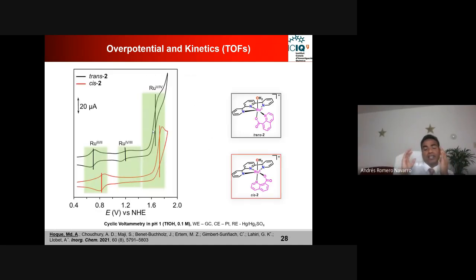So again, this is cyclic voltammetry. That is a very good analytical technique and assay to define the catalytic activity, the turnover frequency, the overpotential, and many, many other things. So here, these are the redox spots. For example, here we have ruthenium-2, and we are removing one electron from ruthenium-2 and generating ruthenium-3. And as we are removing the electron, it's giving this current response, and that is why it is giving the bump. And with this bump, we decide the redox potential of that system.